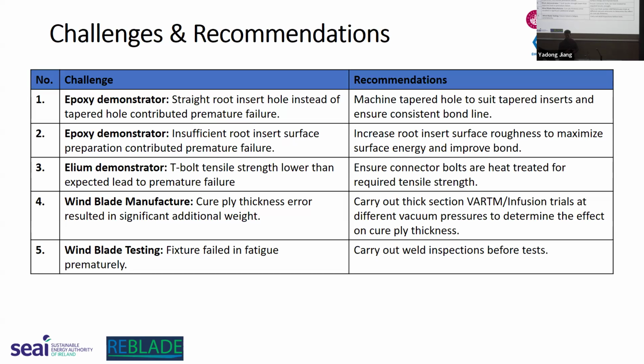miscalculated the cure ply thickness for the 30-meter blade, and that resulted in a significant additional weight. So we did a thickness trial where we compacted a 40 mil thick section, and then we calculated how many plies are in that under full vacuum, but we didn't do it at 750 millibars. So we put in more glass fiber plies than we needed, and that increased the weight of the blade significantly. And that's probably why we didn't see much fatigue failure in the blade, because it was a lot heavier than we expected and a lot stronger than we anticipated. But it does show that there's a lot of room for reducing the weight of the blade and optimizing the layup.